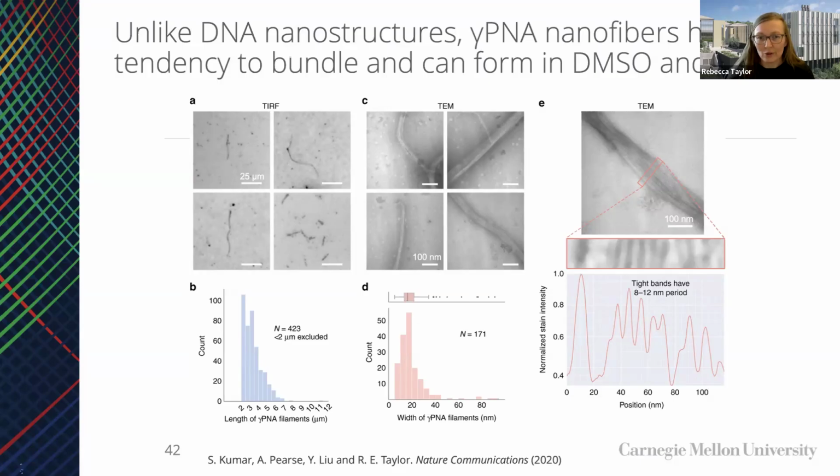It also does triplex binding, right? So it raises all these interesting questions about how should we be moving towards something like PNA origami. And at present, in this paper, basically, we titrated in increasing amounts of DNA into the structures. But our goal for a lot of this work was to make entirely PNA structures. And the biggest issues that we would see is, as this slide highlights, you get behavior that's not like purely DNA. Without that charge, you start getting the sort of peptide-like behavior you might expect where you get a hydrophobic core, and things sort of tend to crash together.